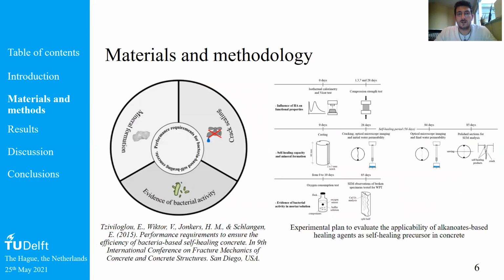In order to evaluate the applicability of these healing agents, a former PhD of our department at TU Delft, Emanuele Rossi, proposed three factors of performance that need to be evaluated when investigating the applicability of a certain healing agent in terms of its self-healing capacity. These are the occurrence of mineral formation thanks to the healing agents included, the regain of water tightness, so the crack sealing capacity of the material, and also the evidence of bacterial activity.